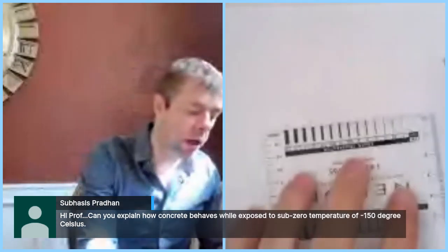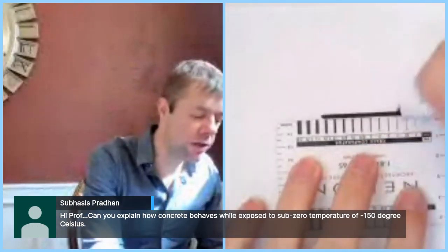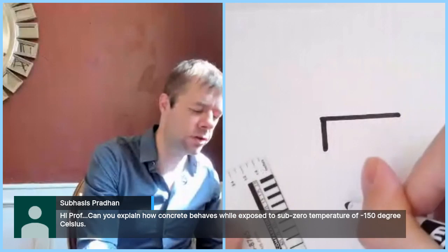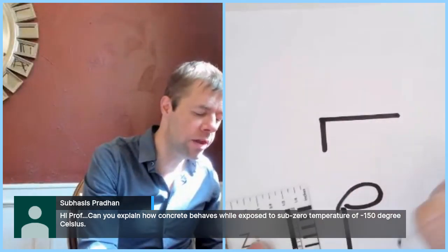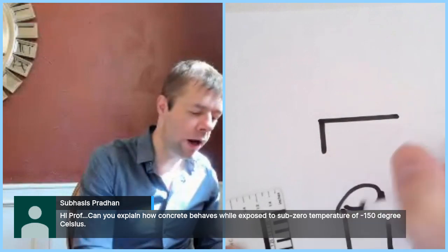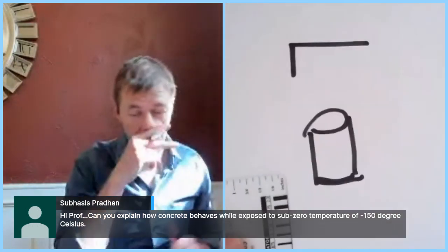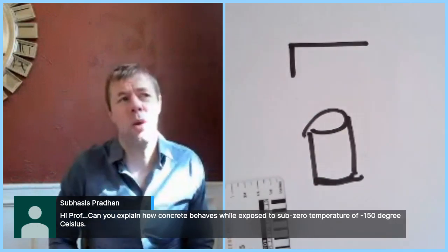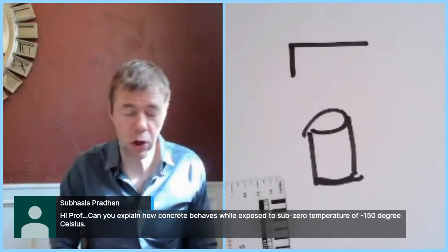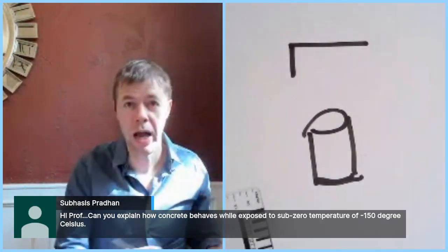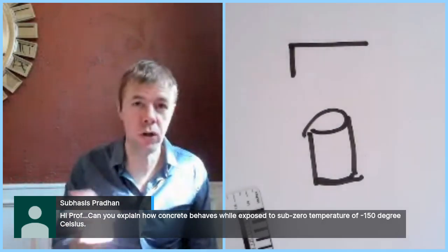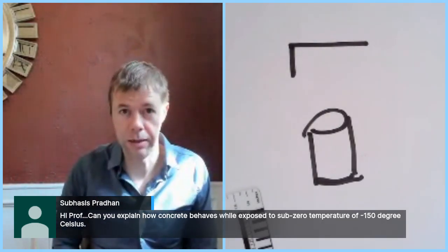What they did, there were two separate people who independently came up with this concept, at least I think they were independent. They took their concrete beams, or I think they were cylinders, and threw them in a bucket of water. They left them in water for several days. I think it was 6 days or so. And then they took the concrete out after 6 days of being inside water, and they immediately froze it. They took it to as cold as they could get it.